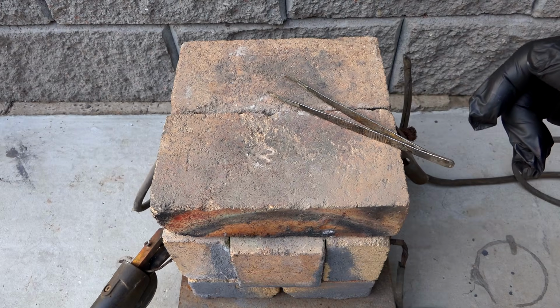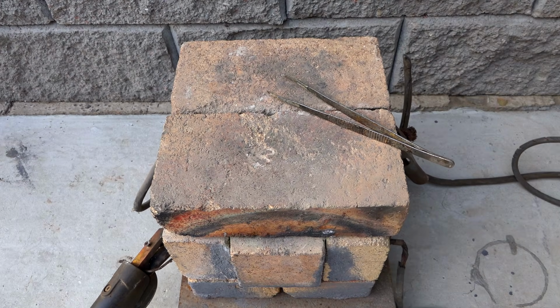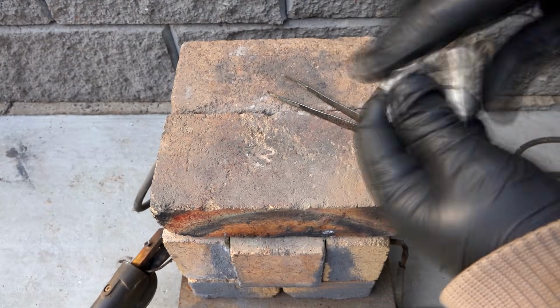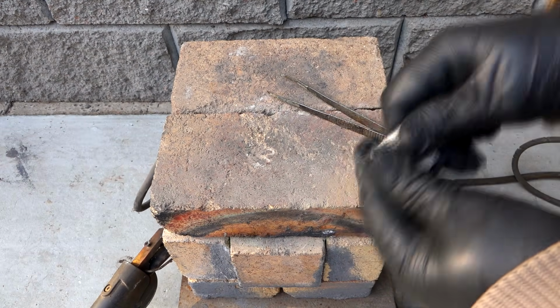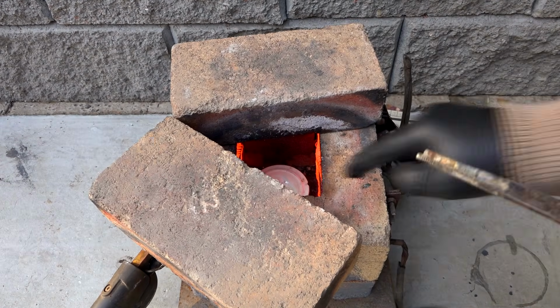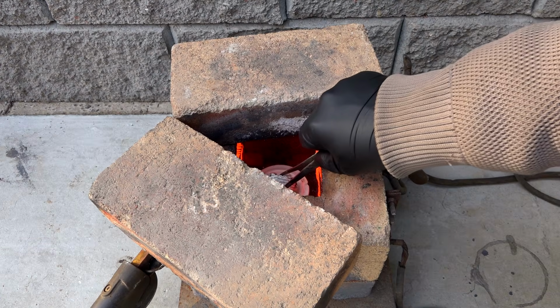Now you can fuse the filtered precipitate together with the filter; the paper will burn, and the gold will fuse into an ingot. At this point, a small problem occurred. During the folding of the filter, it began to crumble. This is due to the effect of sulfuric acid on the paper after filtration. But I noticed it in time and just wrapped everything in another piece of paper and didn't spill anything.